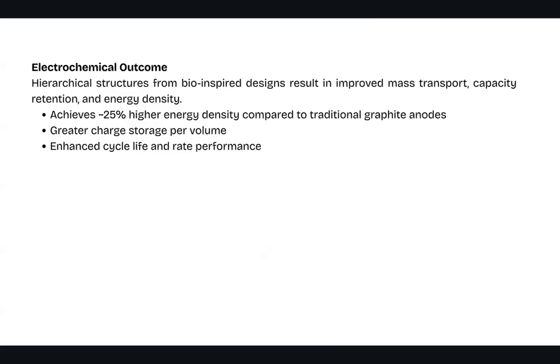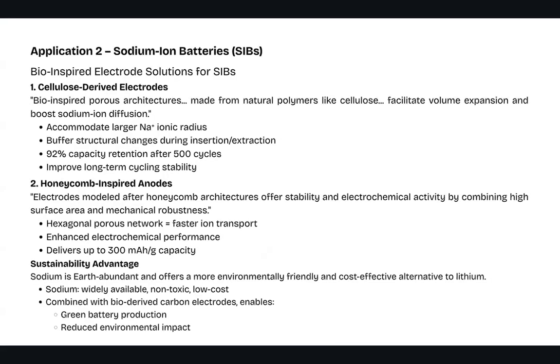So what is the electrochemical output from this? Hierarchical structures from bio-inspired designs provide improved mass transport, capacity retention, and energy density. So it basically achieved 20 to 25% higher energy density compared to the traditional graphite anodes, greater charge storage, enhanced cycle life, and rate performance. From here, Sanju will continue.